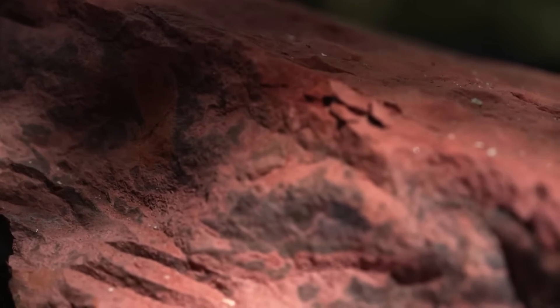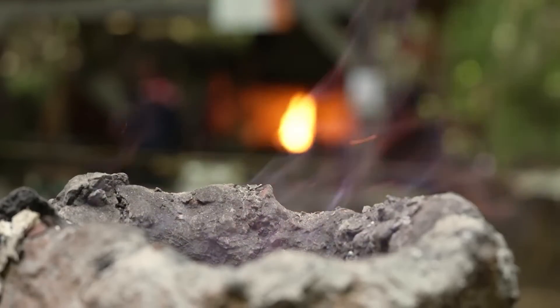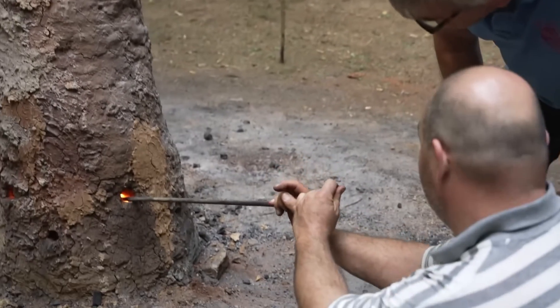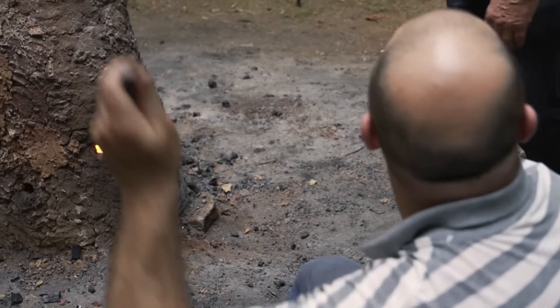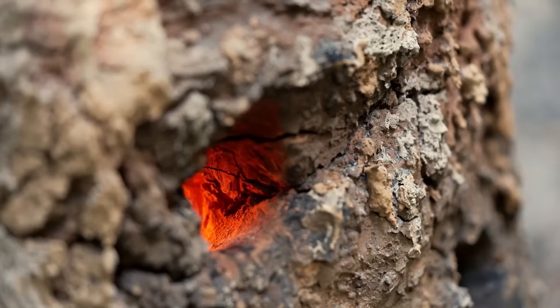It's a nice-looking red ore with hints of brown. The richer in iron the hematite is, the darker brown or even gray it will be. We're nearing the bloom stage — it's nice and soft, very good sponge iron. The temperature inside is 1,150 degrees Celsius, what we call the forging zone. It's when the metal can agglomerate and become malleable.